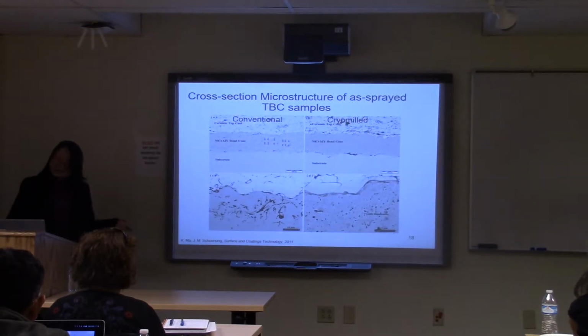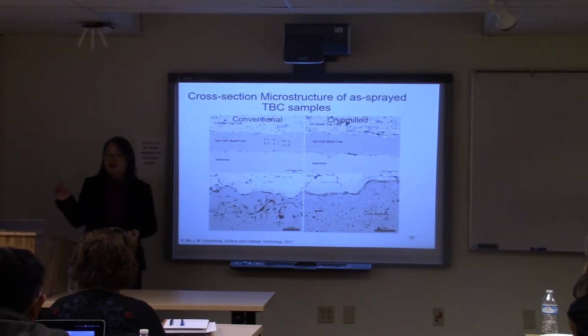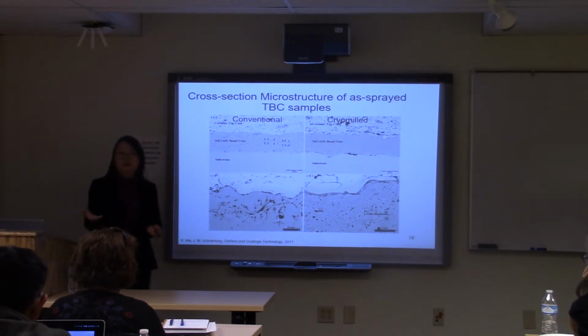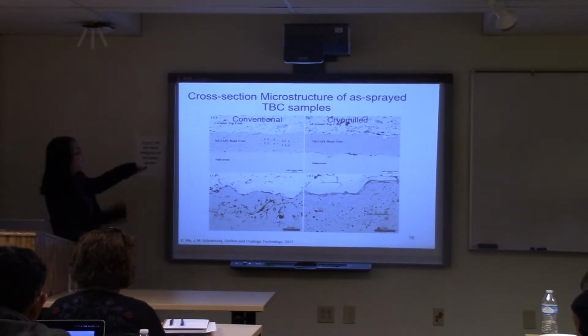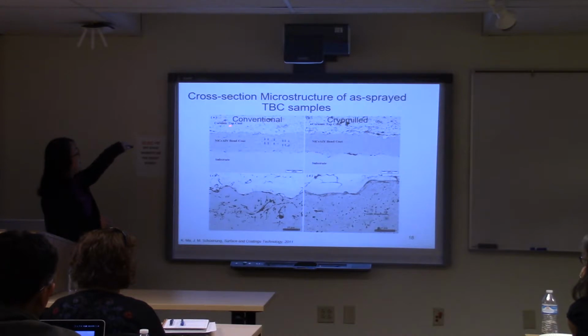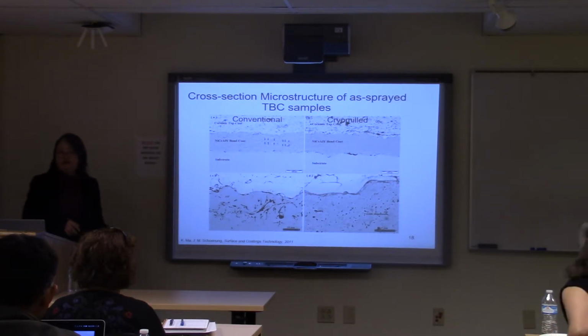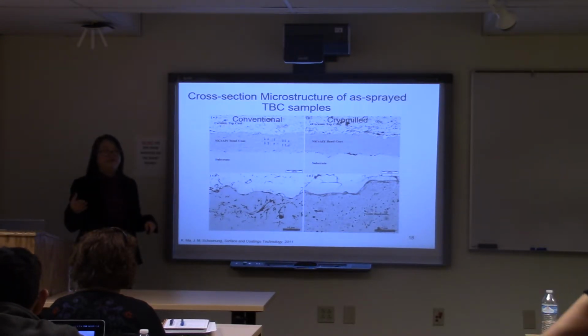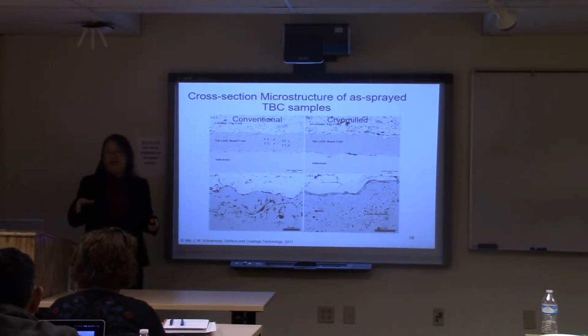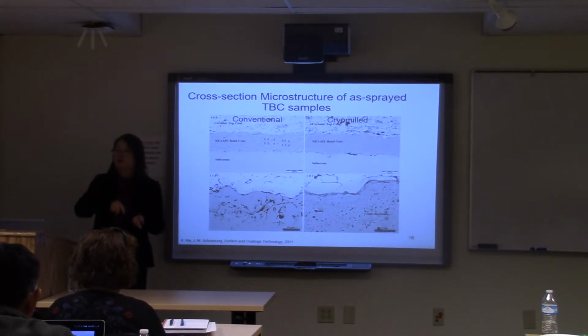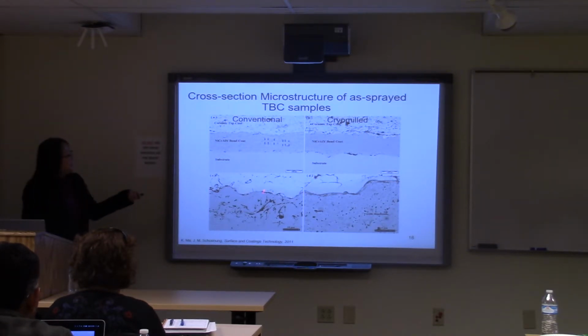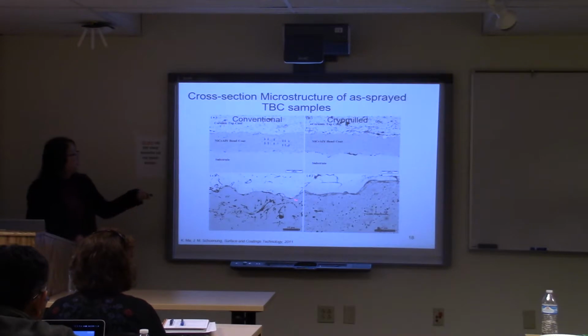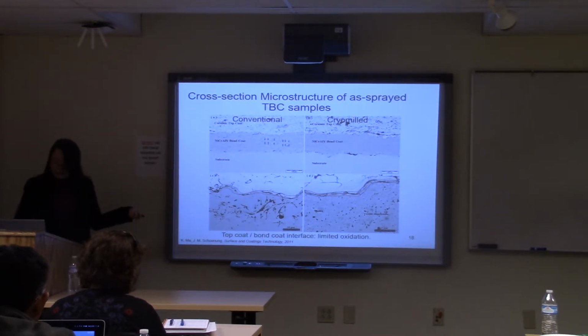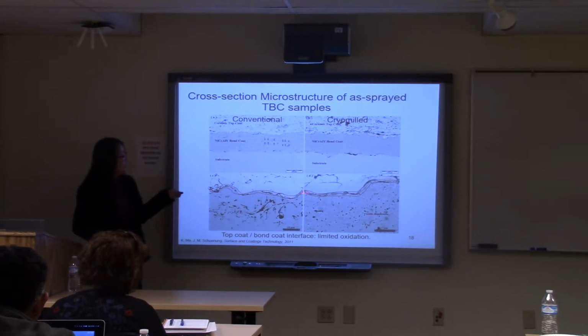After understanding the microstructure of the bond coat itself, it's time to see how this microstructure will contribute to the oxidation behavior. So now we zoom out to look at the three layers. If you recall, the whole thermal barrier system has the top coat, bond coat, and substrate, and this interface is where the oxide will form. We would like the oxidation behavior to be more homogeneous, otherwise you might get stress and the top coat will spall off from the substrate. This is the as-sprayed condition, and if we look at the interface here, we only get very limited oxidation.